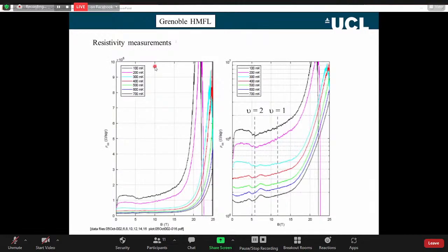So this is what happens at high field. This is device resistivity now as a function of magnetic field, up to 25 Tesla. At higher fields, the device really does go resistive. On the left-hand side here we've got device resistivity, and you see it's going up to 10 megaohms. That's a four-contact resistance measurement, very difficult to do. It's also in a fridge. We can go down to 100 millikelvin. So it's very sophisticated equipment. The device measurements themselves are a little bit awkward.